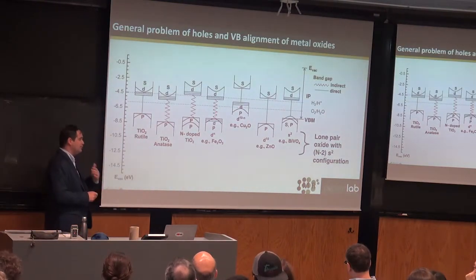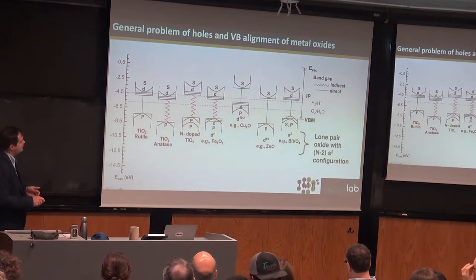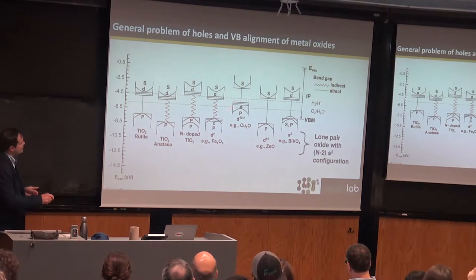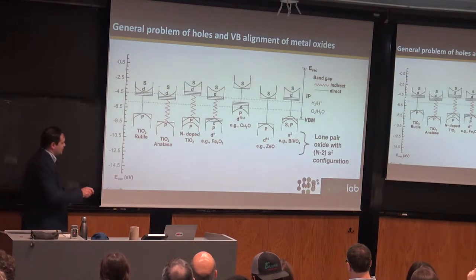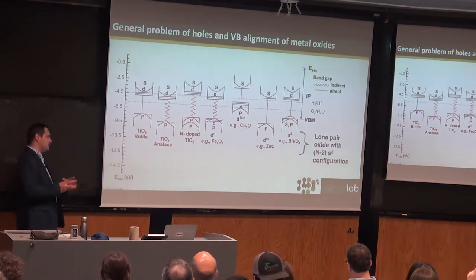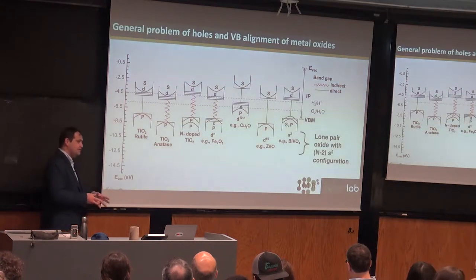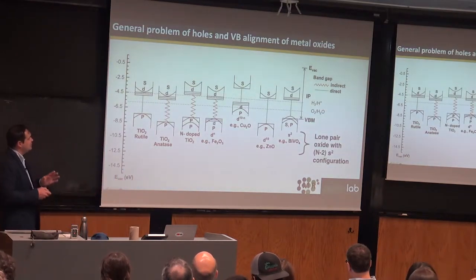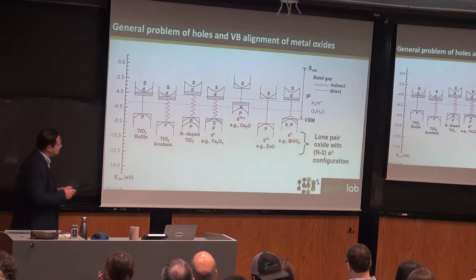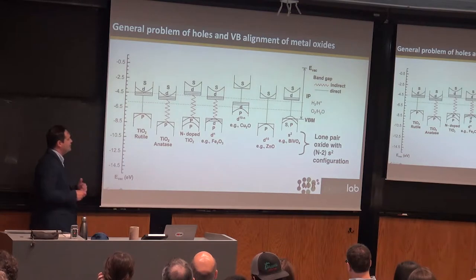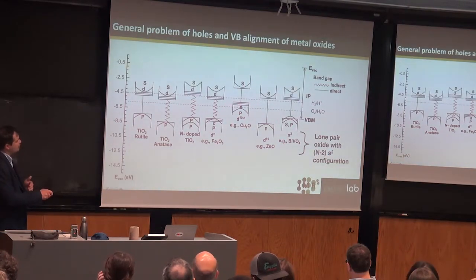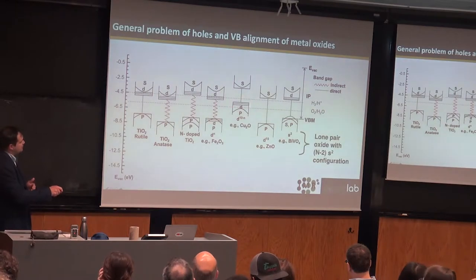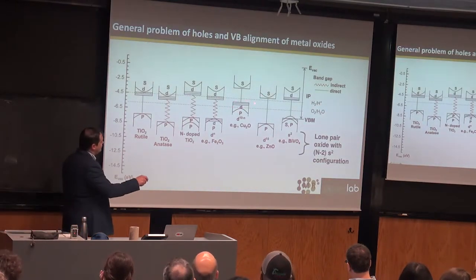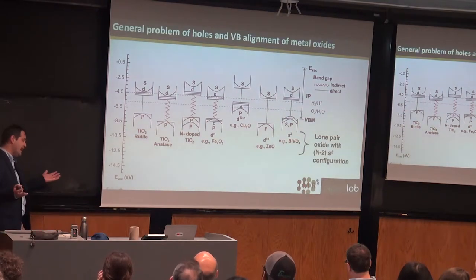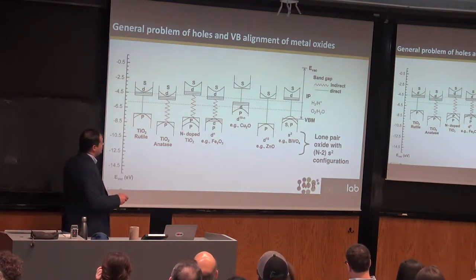So then you're talking about your 3d transition metals, where you play with the degree of hybridization, where you have d orbitals mixed with your p orbitals to drive up your valence band maximum. In this case, this can lead to some undesired properties. You want it to be a direct band gap, so it's not just the right band gap, you want it to be direct. The other thing is you might overshoot in the case of copper oxide, and the other thing is you still might have, even in copper oxide, you can form holes because you reduce this energy difference to allow defect formation, but the other issue is you still have d orbitals which are pretty flat, and so you have poor mobility. So the trick is, how can we get around this?